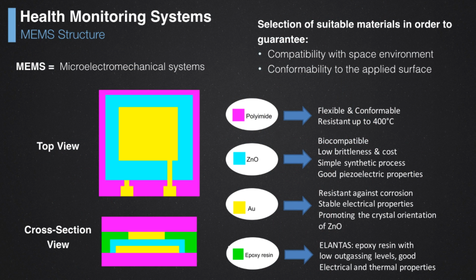We deposited a typical sandwiched capacitive structure with parallel plates using gold electrodes. Why gold? Because it is a noble metal which is not sensitive to oxidation, not reacting with oxygen easily. And in between the two parallel plate electrodes, we placed the active material, that is zinc oxide. Afterwards, we used a binding resin, which is a kind of glue. In particular, we used an epoxy specifically designed for space application, the ELANTAS material, to glue together two polyimide foils. This was done in order to seal completely the device and avoid